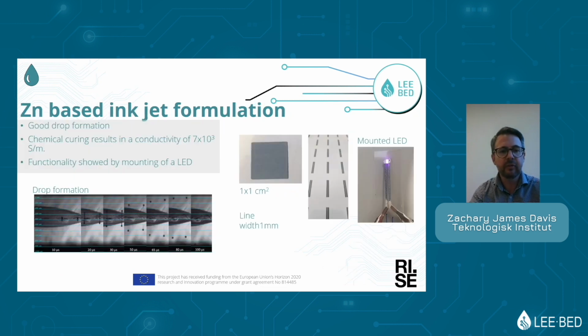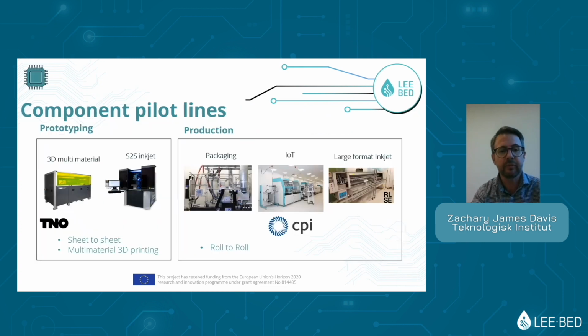RISE has also been looking into formulations of other more cost-effective materials using zinc-based inkjet formulations. In this case, they have quite good conductivity using extremely cheap zinc nanoparticles. And instead of using thermal or photonic sintering, they're using a chemical sintering process. You print first with your zinc, and then you print on top of that a chemical curing agent, which cures the zinc, and they are getting quite good results. So zinc is another alternative to silver for a cost-effective, highly conductive material.